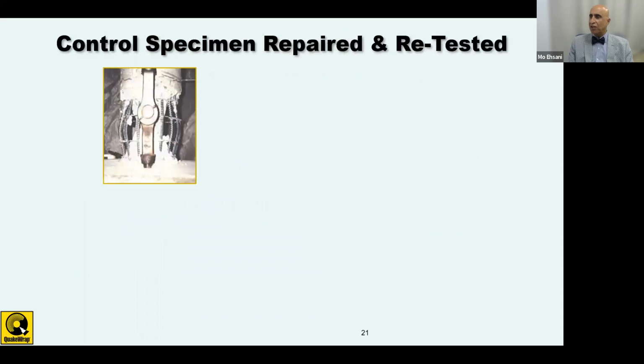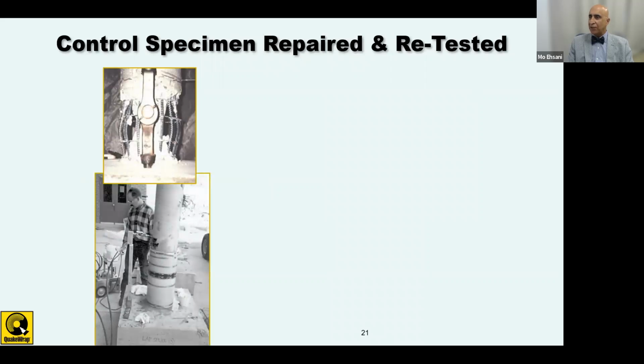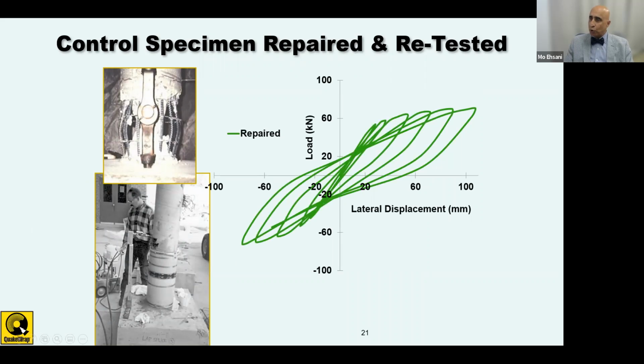In fact, as a part of this study, we took the same specimen that you saw before, cleaned up this bottom portion of it, and wrapped it with some of that FRP product that I was showing you before. Once the bottom couple of feet were wrapped, we injected resin to make sure that all the voids and cracks were filled and became solid. Then we took this same damaged and now fixed column and subjected it to the same type of loading.